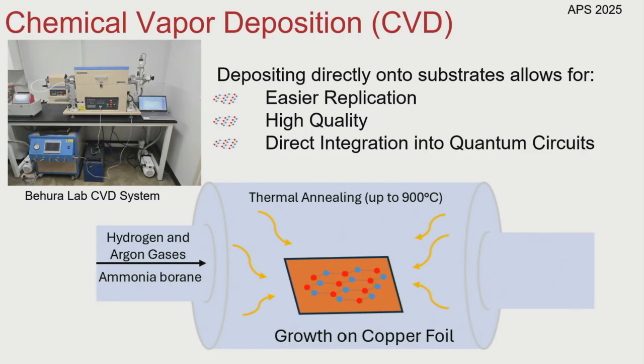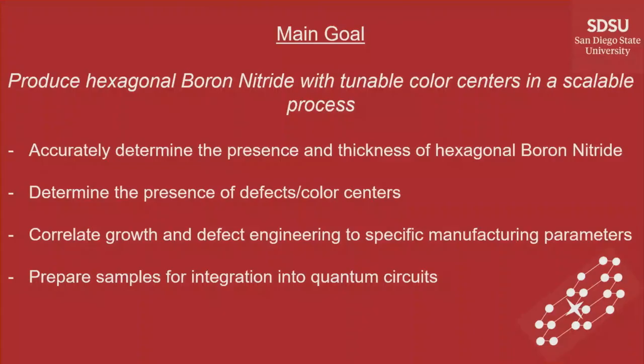temperature, and most other labs that utilize this process deposit those on a catalytic substrate, as shown here with a copper foil. This allows for easier replication. It can be pretty high quality, although not perfect like the bulk crystal exfoliation that we've seen before, and we can hopefully directly integrate this into a quantum circuit at a larger scale.